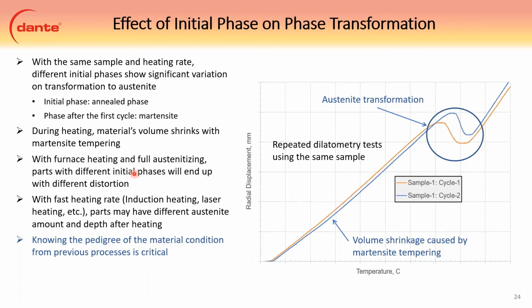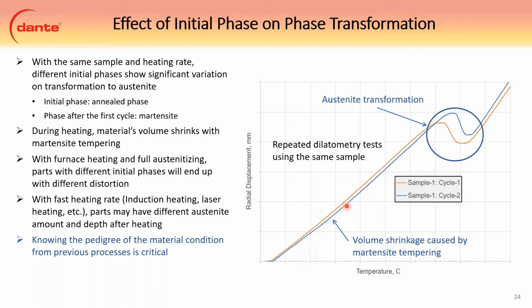The effect of initial phase on phase transformation. The first cycle here is the annealed condition, most likely ferrite pearlite. And then this blue line is the retest of the same sample after being quenched to martensite. So this blue curve starts as martensite, and this volume shrinkage that you see here is actually the material being tempered at high temperature. And then you can see the effect on the transformation strain and the total strain from the austenite transformation.